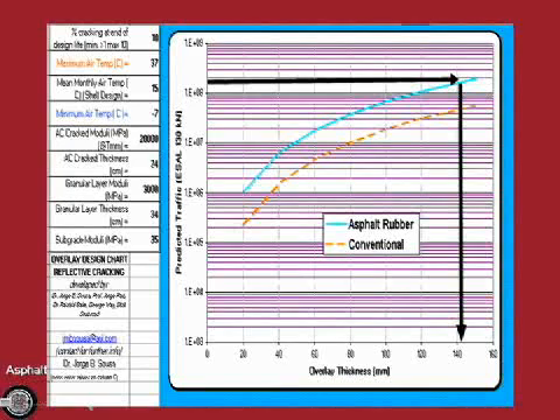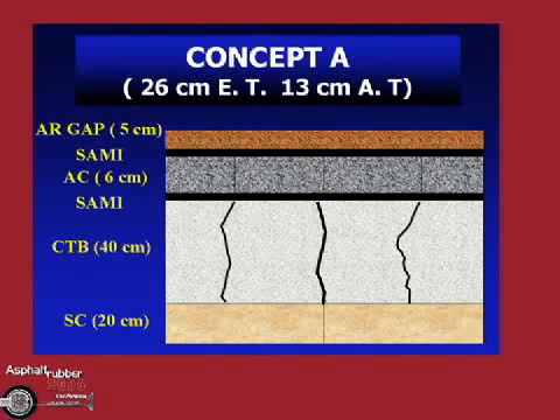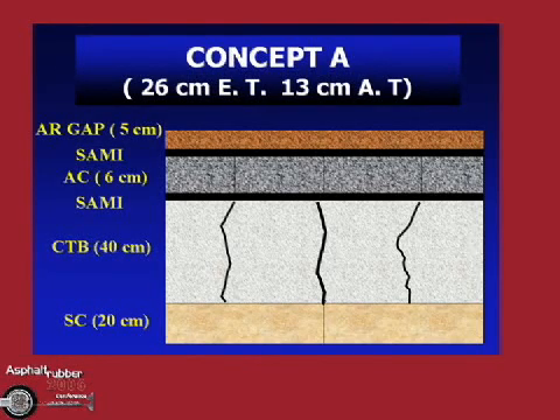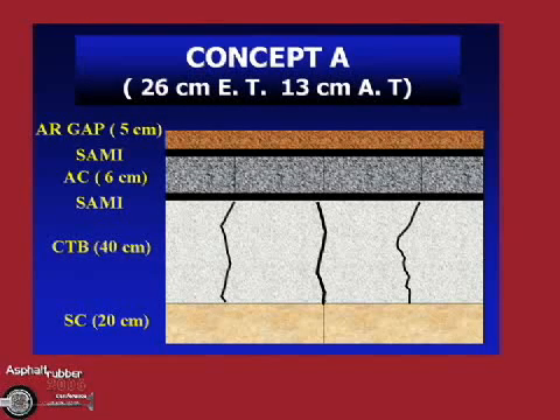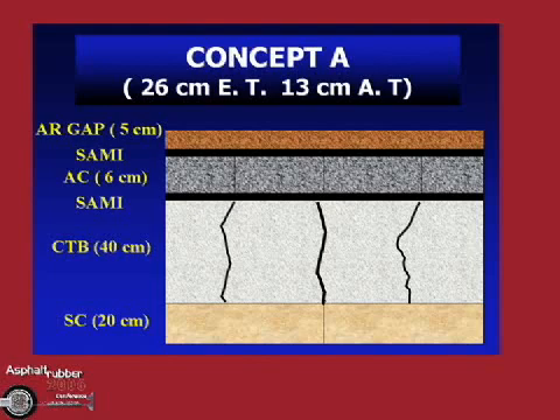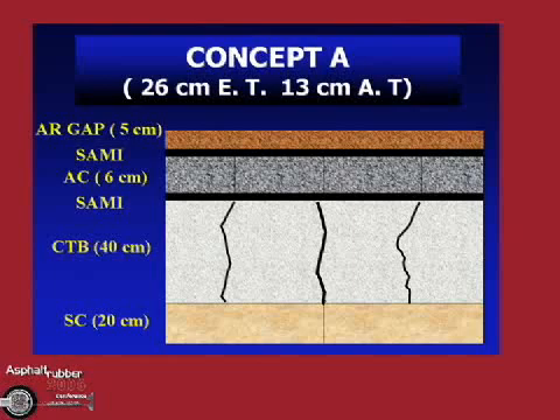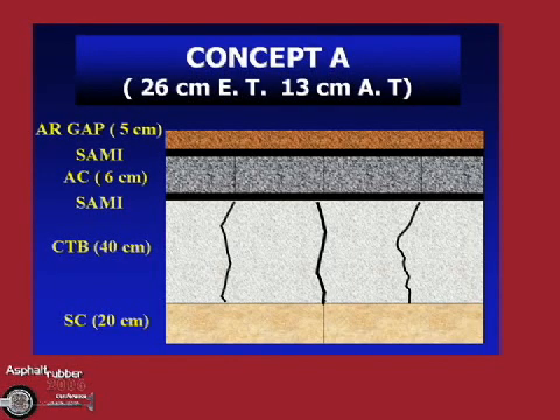So then the concept came: why don't we make new pavements that actually can crack, and they are cheap? Making new pavements with cement-treated bases in China. They have very poor aggregate, so everything is cement-treated. You can go heavy on cement, let them crack. Then, this base is strong because they crack from shrinkage, not from, no, this is a strong pavement.